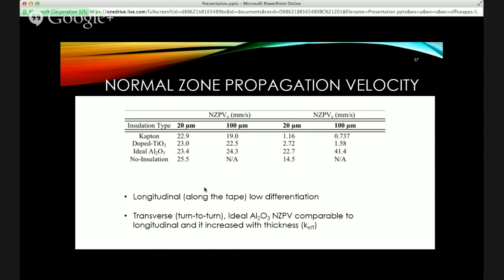But if you move on to the transverse direction, you now see that for ideal alumina, it is nearly the same as its longitudinal direction, which is a good thing, because that means that now, if we're having this growth of this normal zone, we can either detect it earlier because it's spilling to the different turns, to the different layers, or we're reducing the temperature because all of the thermal energy is not confined to just a single conductor. So it's interesting to look at, moving forward now, how we consider insulating these coils.